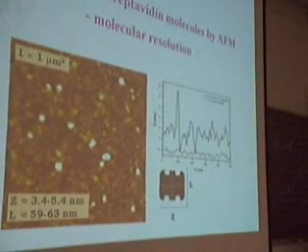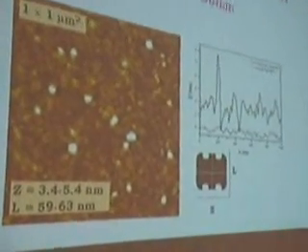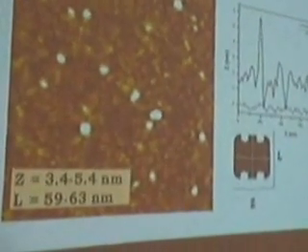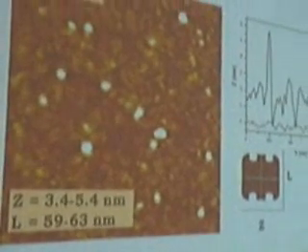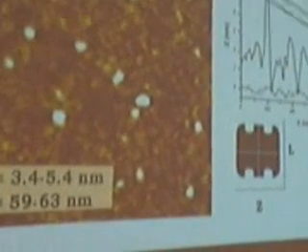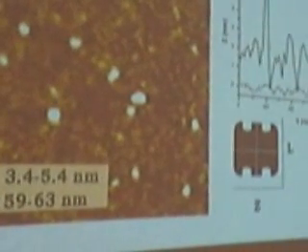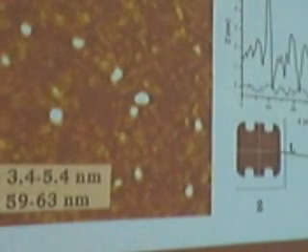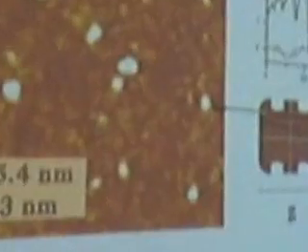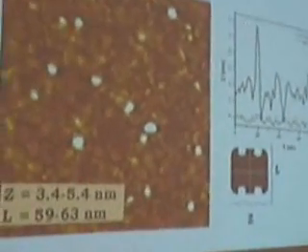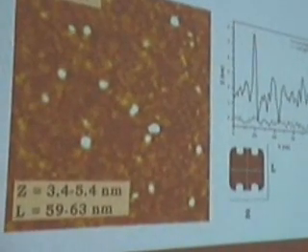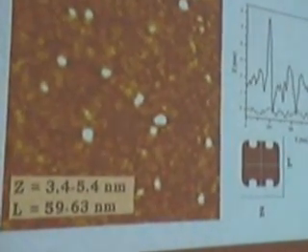Well, in order to be sure that we actually have succeeded in this, it's nice to demonstrate that all this is there and is functioning well. So we use, for example, AFM to demonstrate this, by taking topographs with AFM, and we get molecular resolution and actually can see where, for example, in this case, the immobilized streptavidin molecules are. We have on purpose used a very low concentration of these in order to be able to see individual molecules. We can increase, of course, the yield of adsorption if you want by increasing the concentration of these in the solution.